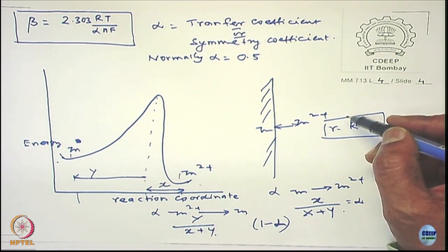The difference between I and I naught is that at I naught, there is no net oxidation or reduction, but when it is I, it is either an oxidation or reduction process. I naught will change if you change the concentration of species, or even the temperature. But all it means is it is an equilibrium and no oxidation, no reduction takes place. I am not going into details. I am discussing electrochemistry only to the extent that you can understand corrosion better. There is no way a comprehensive treatment of electrochemistry, okay.